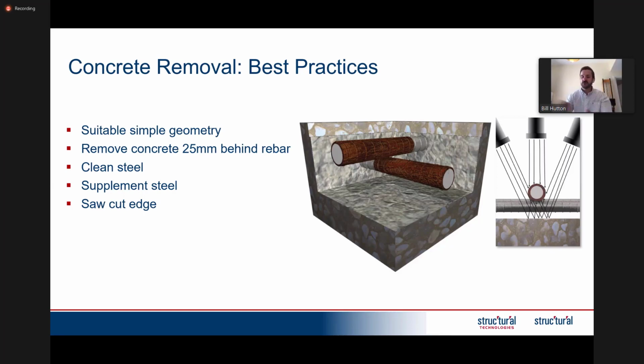The reason for that is two things. One is that you make sure that you remove all of the contaminated concrete around the steel. This steel is probably corroded because it's either contaminated by carbonation or by chloride, so it's important to remove all that contamination. And it also enables you to remove any of the non-tightly bonded rust. The non-tightly bonded rust is typically removed by some means of abrasive blasting. Once the rust is removed, you can then take a caliper.